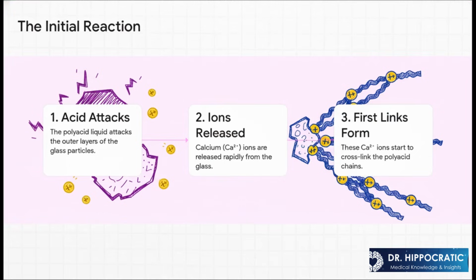1, the polyacid goes on the attack, dissolving the outer surface of those glass particles. 2, this causes a huge, rapid release of ions, especially those calcium ions. And 3, these positively charged calcium ions are immediately drawn to the negatively charged acid chains, and they start building bridges or cross-links between them. This is what makes the material go from a liquidy paste to a solid.